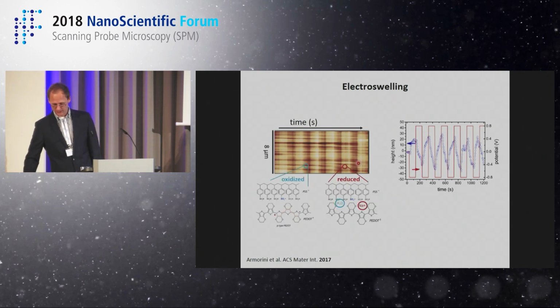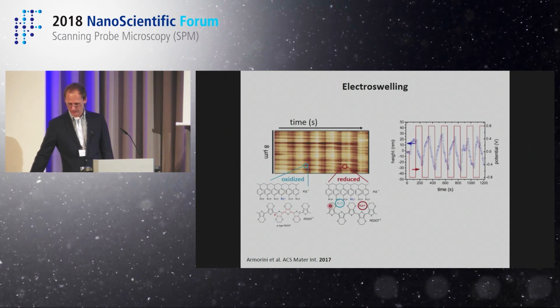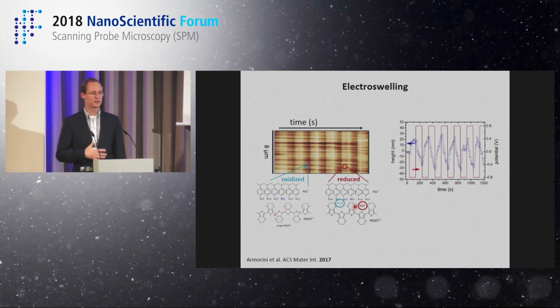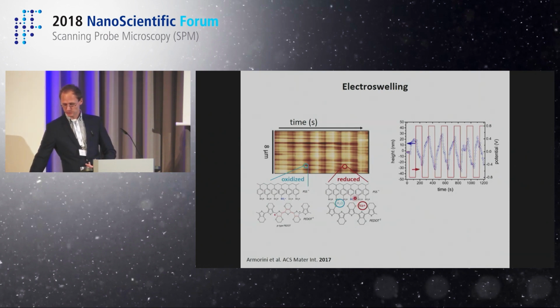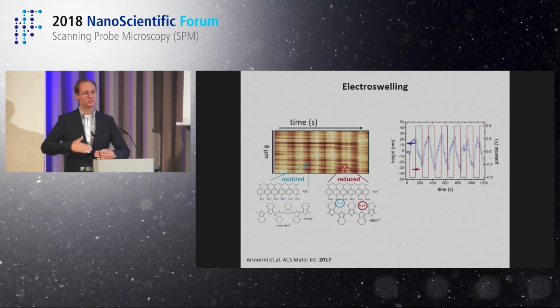Why is that happening at the end? I can also understand it. Not so difficult, because when you're in the oxidized system and the reduced system, the oxidized system does not contain ions, while the reduced system does. And the ions, of course, have a liquid shell, so it's clear that more volume enters into the reduced system, so it's where I observe the swelling, the increase in surface height.